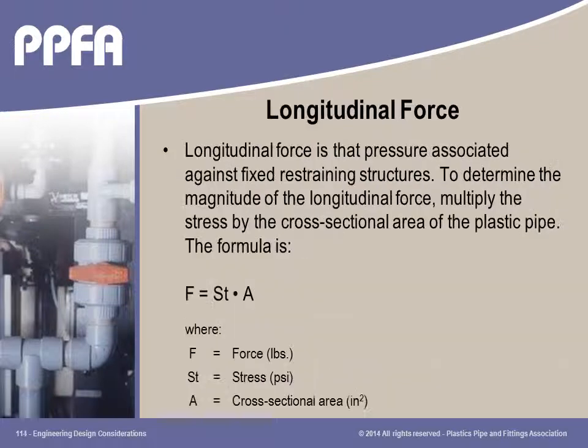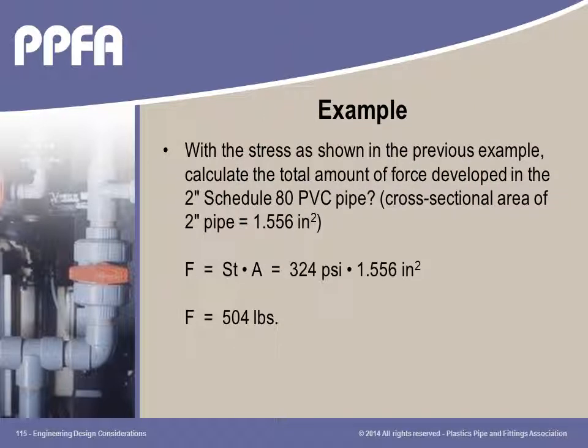pressure capability. The longitudinal forces generated in thermoplastic piping are normally much less than metal piping systems due to lower thermal stresses of plastics. This means a metal pipe could generate enough longitudinal force in a restrained system without proper design for expansion to break brick walls, while plastic pipe, under similar conditions, would tend to bend or fail without affecting the restraining barriers. In this example shown, 504 pounds of longitudinal force was developed.